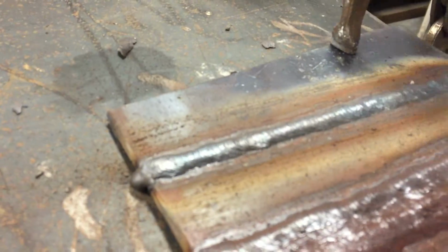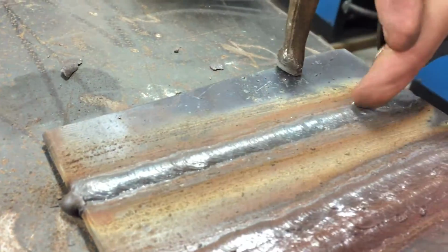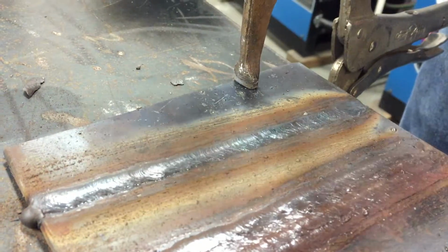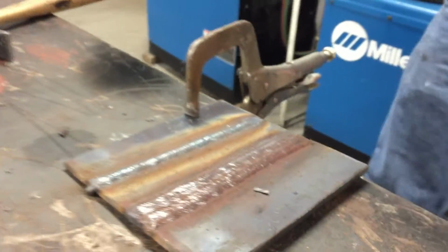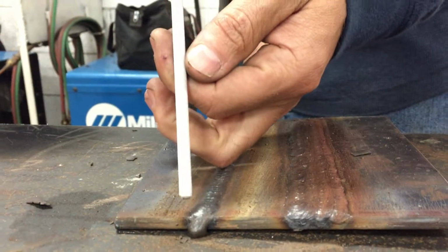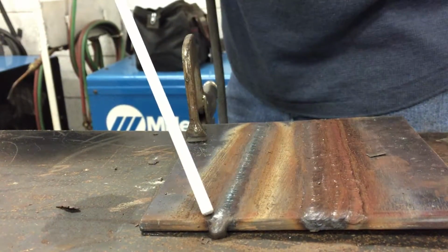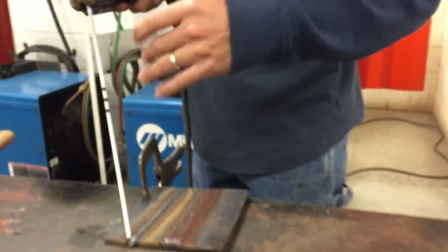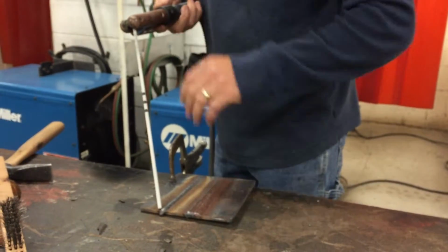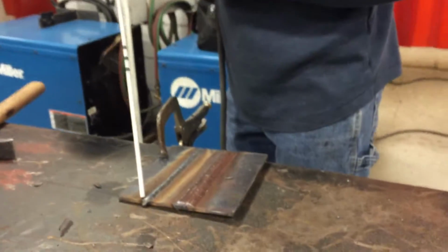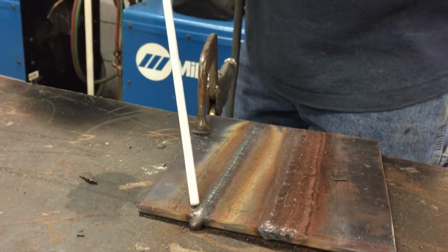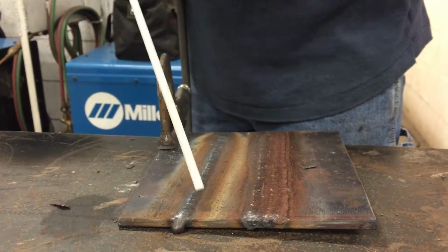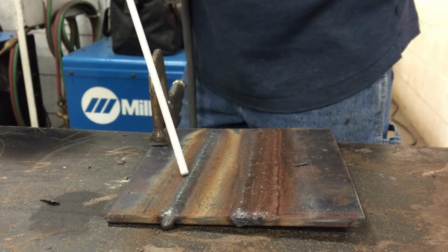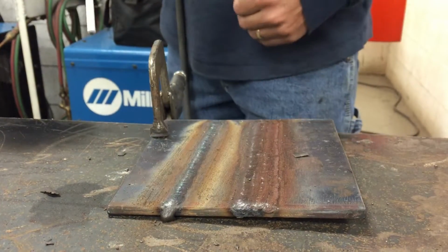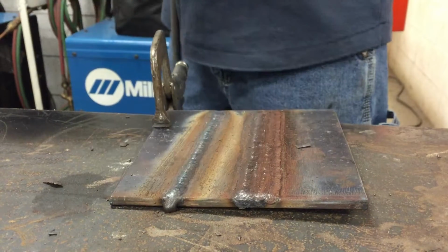Now, to show how to do the next weld. This one was the first weld done with the rod work angle at 90 degrees, approximately 75-degree travel angle. The next weld I would make, I would come in here and I would actually bring the rod and lay it over. Now this can vary depending upon weld height and heat settings. But the key to getting a good multi-pass weld is staying right in the toe of the previous weld. As you come down through here, remember to keep your travel angle the same. As the rod consumes, you have to bring your hands down. But you run your weld right down the toe of the weld. Once you do that, you chip and clean. You repeat this process until you have the size weld desired.